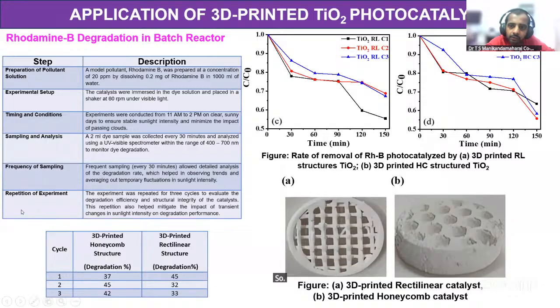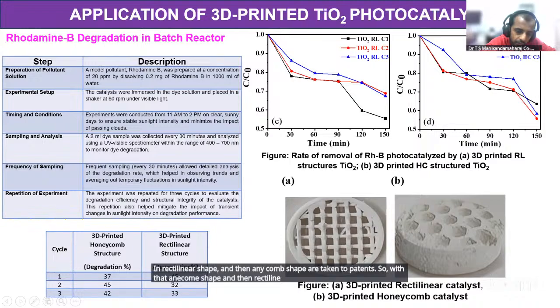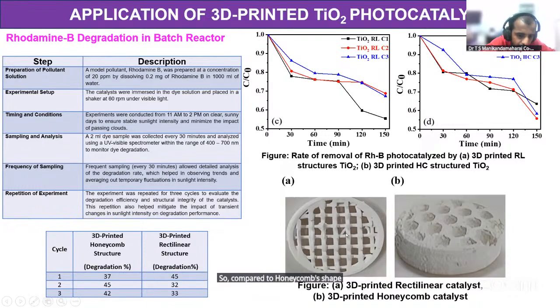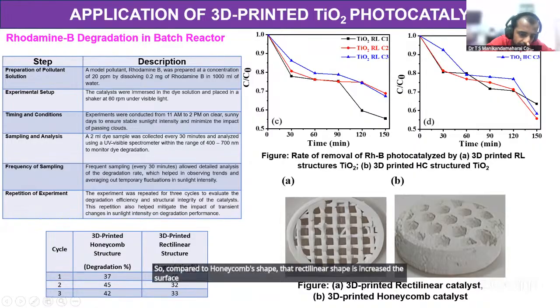In the application of the 3D printed TiO2 photocatalyst, you can see a rectilinear shape and a honeycomb shape; we took two patterns. With these shapes themselves, we can increase the surface area of the material, which is another advantage of 3D printing. Compared to the honeycomb shape, the rectilinear shape increased the surface area of the material, and degradation efficiency increased to 45% compared to 37%.